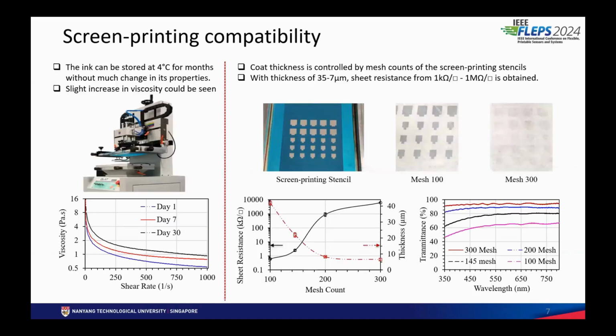And as I said before, we focus on making this process scalable. So we try to optimize this ink for the screen printing process. The ink that we developed, when stored at 4 degrees centigrade, the viscosity didn't change much even after 30 days. Maybe it will be stable even after a few months, but I haven't tested it. We have tried to optimize it for various screen printing stencil or mesh counts, and we obtained about 1 kilo-ohm per square sheet resistance with about 100 mesh count. And this film is as transparent as 80%.